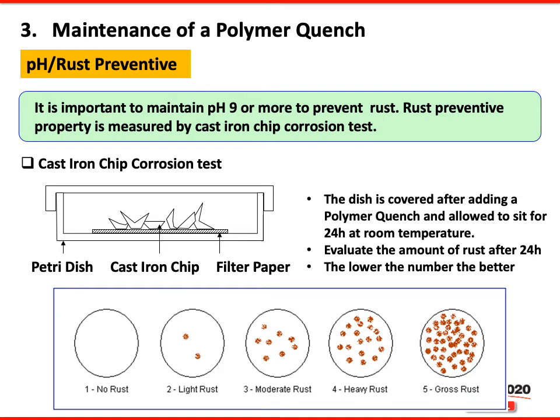Cast iron chip test is how corrosion is measured. You weigh out a prescribed amount of dry machined cast iron chips and put it on a filter paper. You cover it with polymer and allow it to sit for 24 hours. And then you evaluate the rust on a scale of 1 to 5. And you can see a scale of 1 is no rust, 5 is a gross amount of rust. The lower the number, the better.